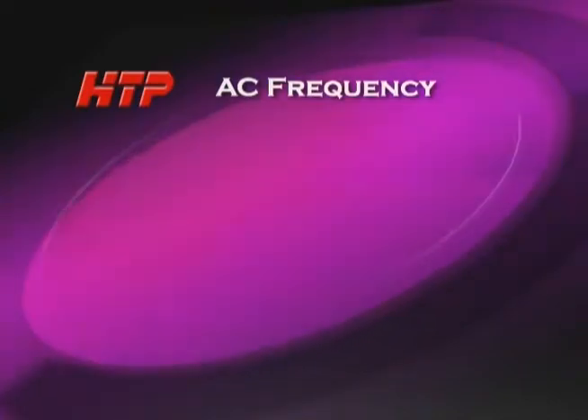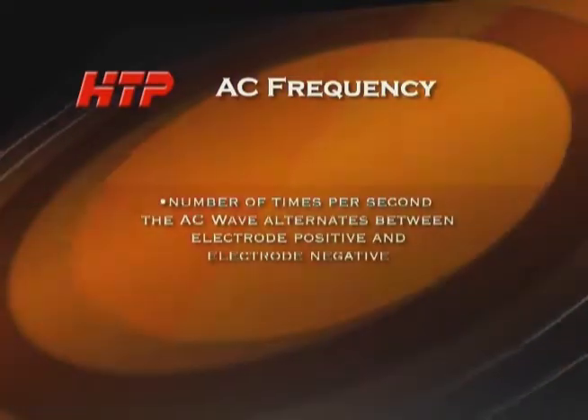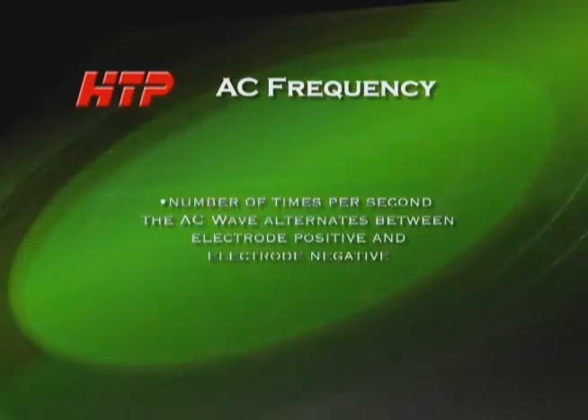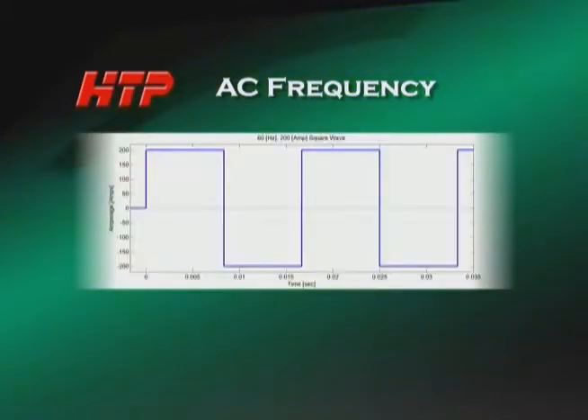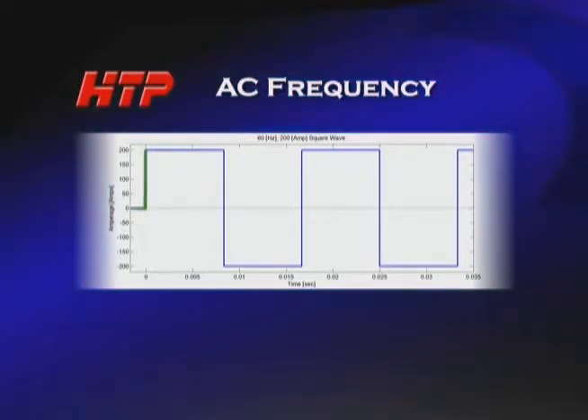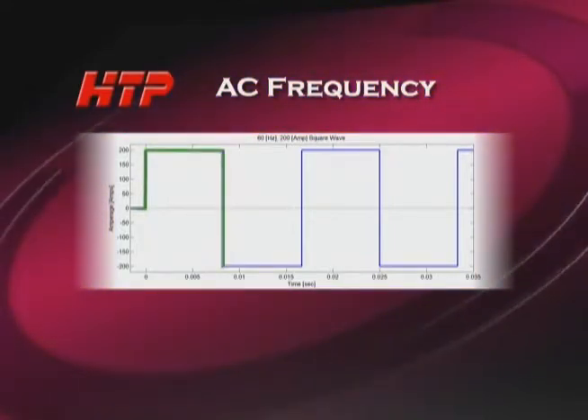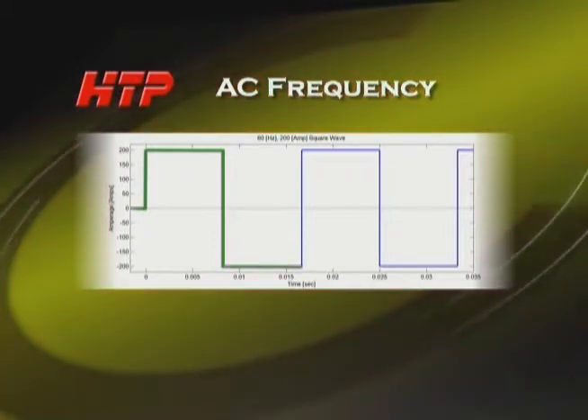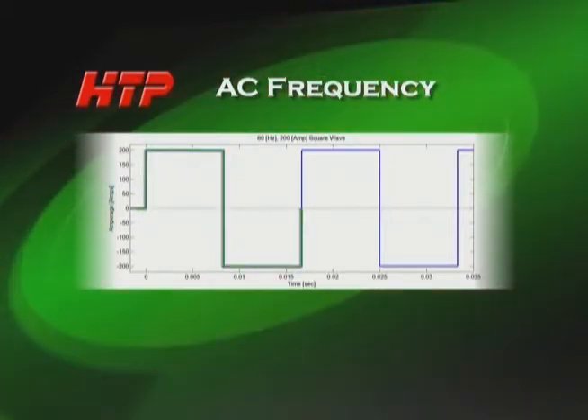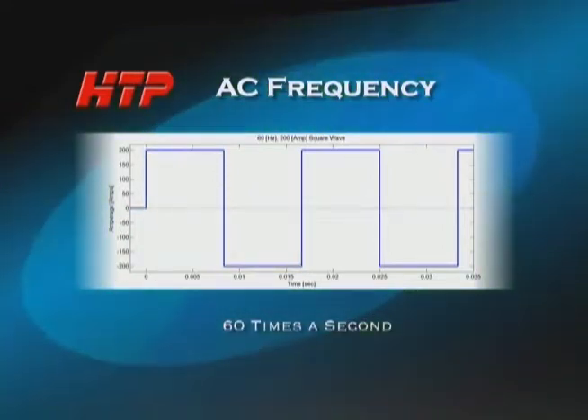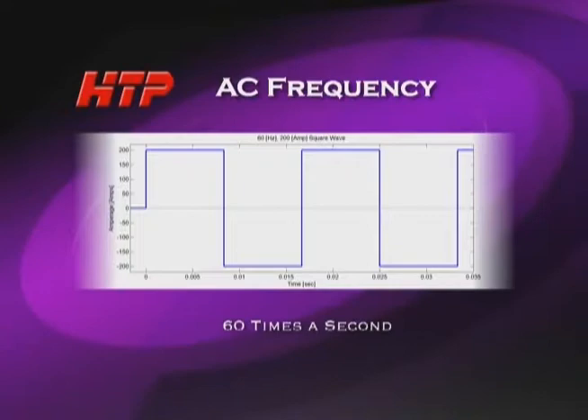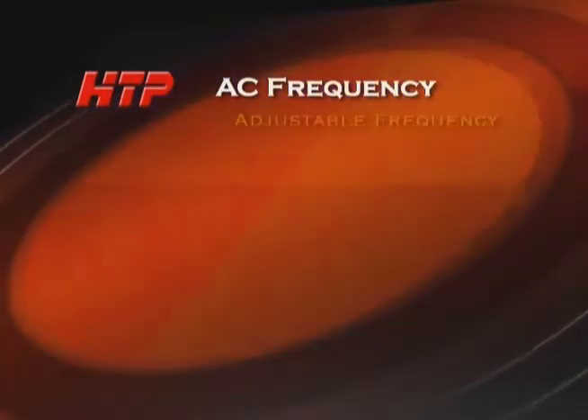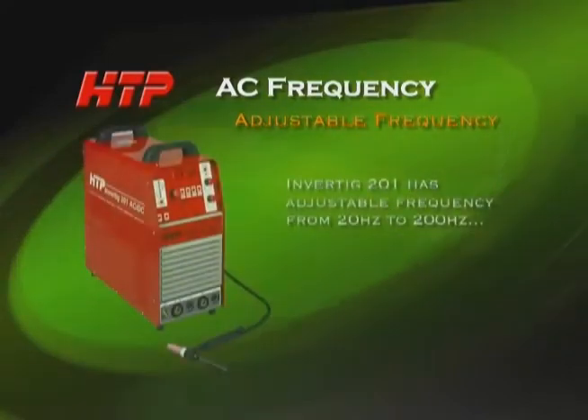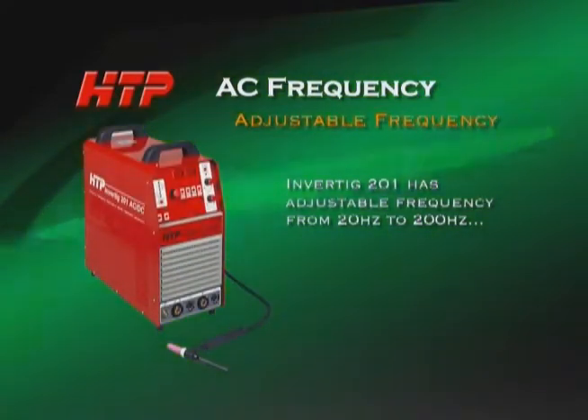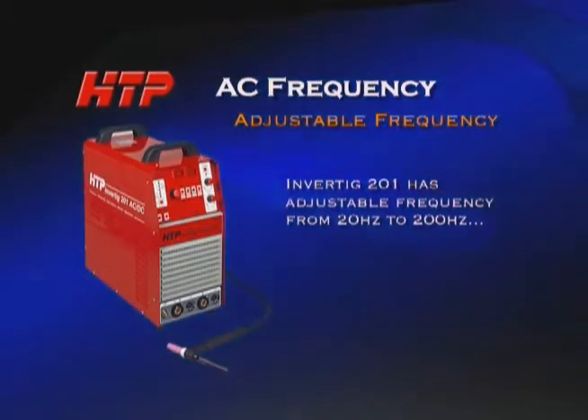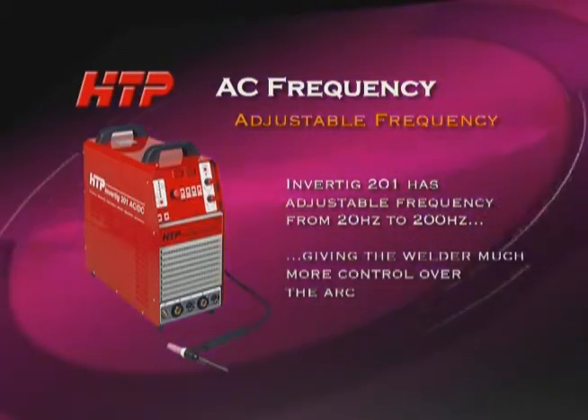AC frequency is the number of times per second the AC wave alternates between electrode positive and electrode negative. The wave starts at 0, goes to positive 200 amps, back through 0 to negative 200 amps, and then back to 0. All this happens 60 times a second. This is a 60 Hz wave found in a conventional transformer-based machine. Adjustable AC frequency is one of the major benefits of the Invertig 201. The ability to adjust the AC frequency from 20 Hz to 200 Hz gives the welder much more control over the arc.